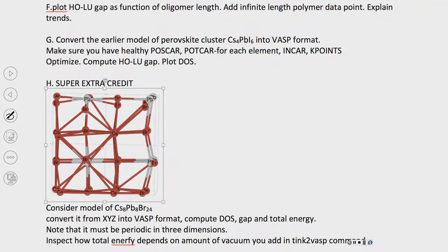If you have a super large amount of time, you can try adding a little bit different amounts, like add 2 angstrom of vacuum, 1.8, 1.6, 1.4, or maybe 2.2, and see which amount of vacuum minimizes the total energy. Daniel knows from his experiment that if you put 0 vacuum, this atom and this atom will smash into each other and the energy will grow substantially.